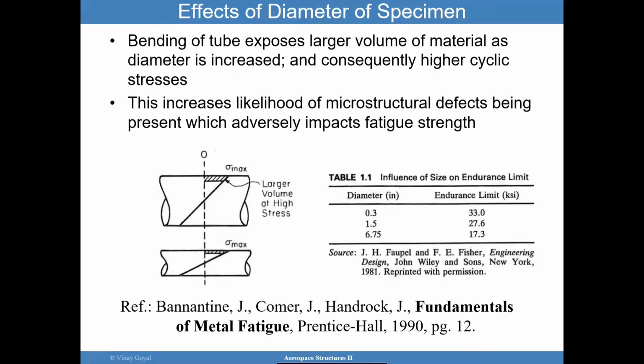So what are the effects of diameter on the specimen? If I have a situation where I have a large material, like a large cross-section compared to a smaller cross-section, and it was a hollow tube, then you have a lot of area under a lot of stress compared to this situation. So it was found that even though I may have this same amount of stress, for a larger sample it can reduce the endurance limit because there's more likelihood of microstructural defects being present when you have a larger area. So there were some size effects being found, and so if I had a 0.3-inch diameter, the sample took longer to fail, even though it had a thinner section, but it had the same stress.